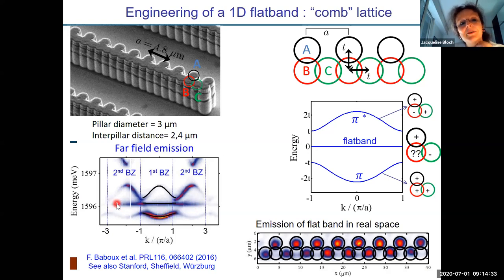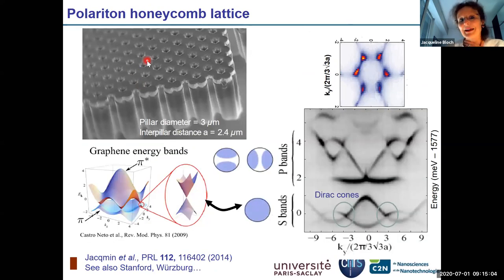And now if you look in real space at the emission, exactly at the energy of this flat band, you see this pattern. You see that indeed in the flat band, the middle pillar, the one where there is this phase frustration, is dark, which is really the signature of the fact that we have indeed this frustrated lattice. So we have here a unique tool to monitor the bands in real and reciprocal space. Another very nice example is the honeycomb lattice of micropillars, which mimics the physics of graphene.